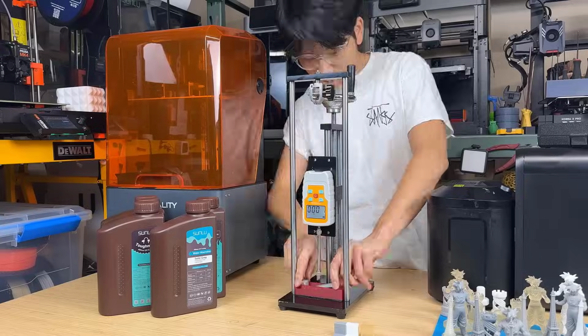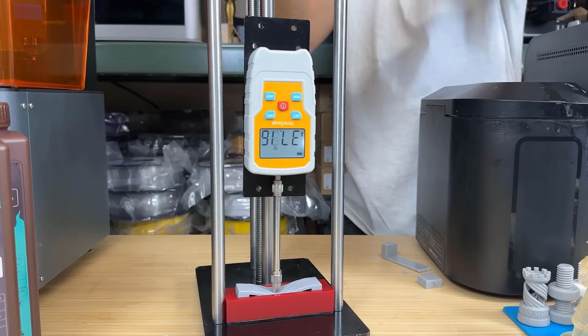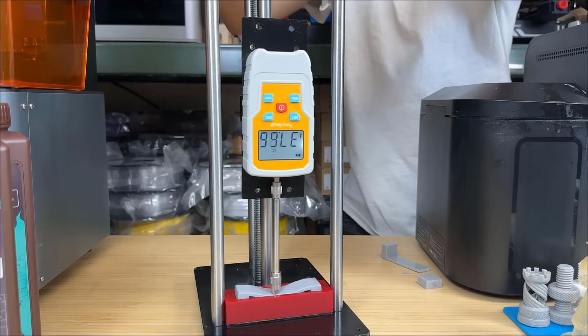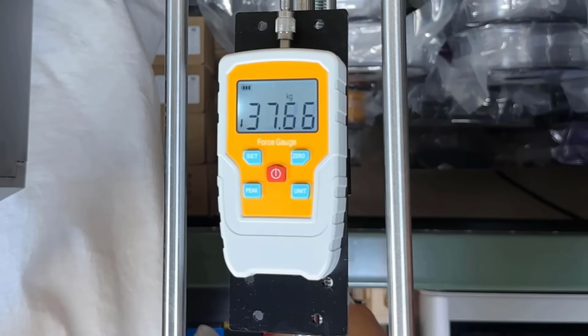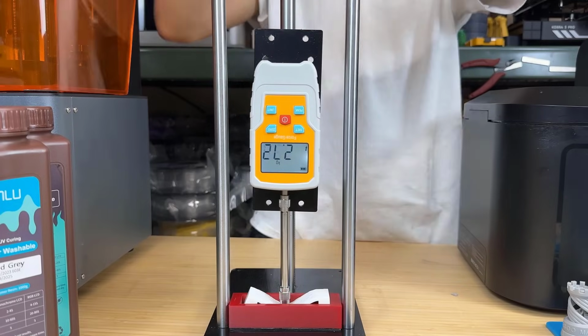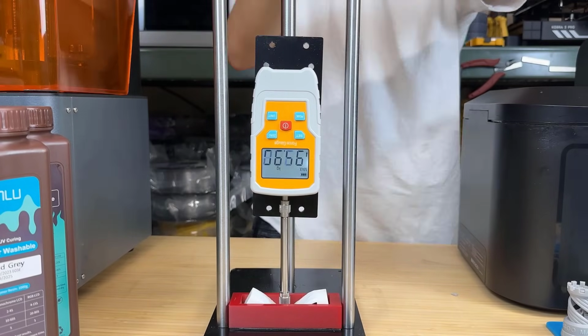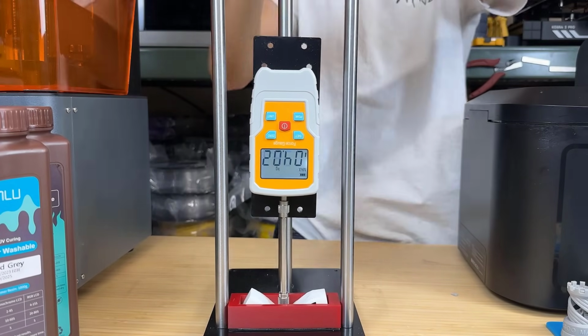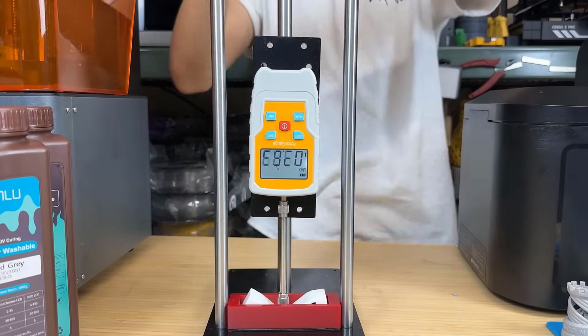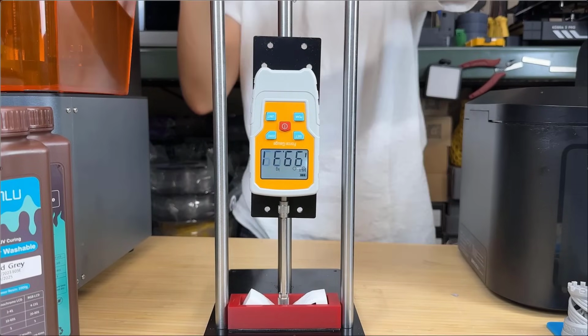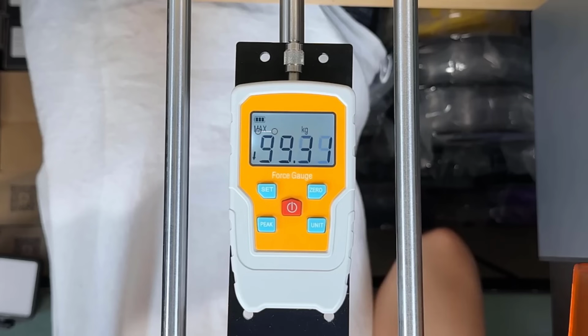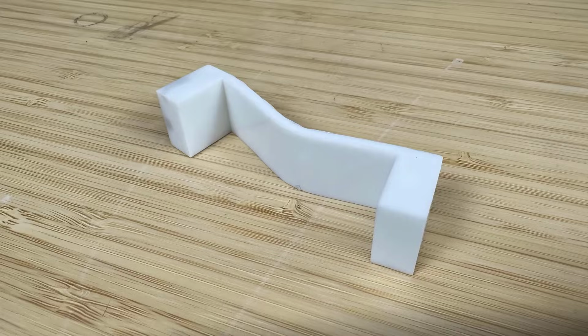Now for the 14K high-resolution resin, the last frame before it breaks shows 16.66 kilograms, which is surprisingly tougher than both the standard and water-washable resins. Then, I will test the tough resin to see how much it can withstand. I applied as much force as I could, reaching almost 100 kilograms, but the part remained flexible and did not break. It could likely resist even higher pressures, but we didn't have the strength to push it further.